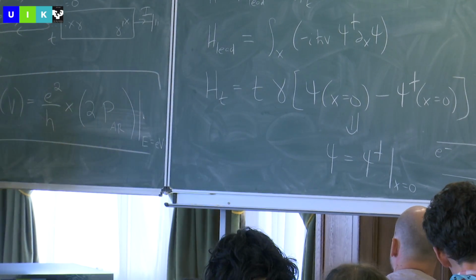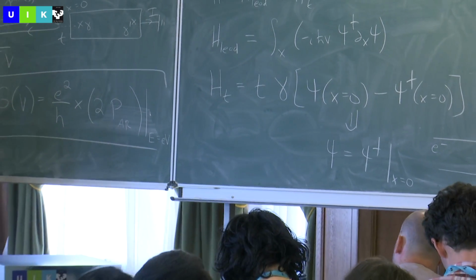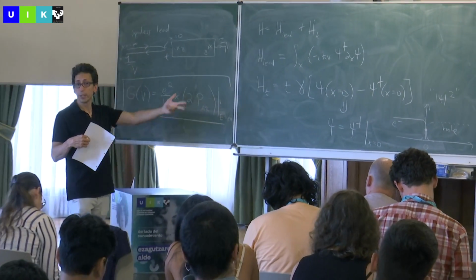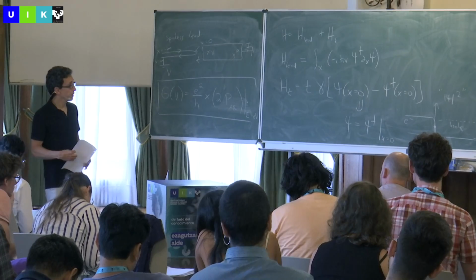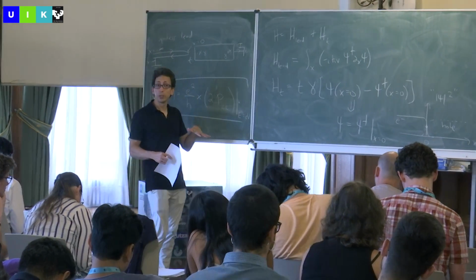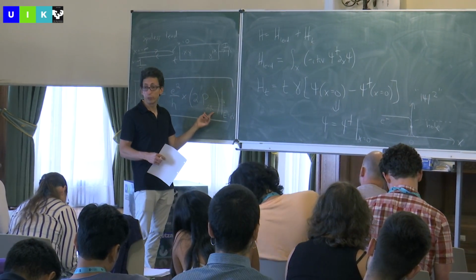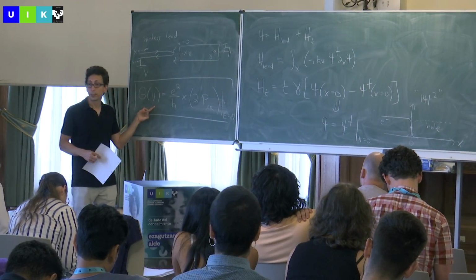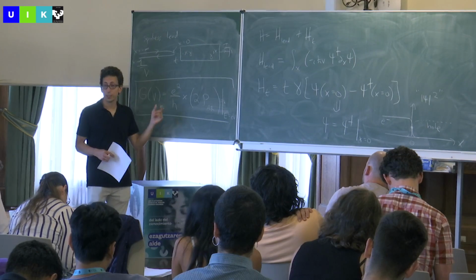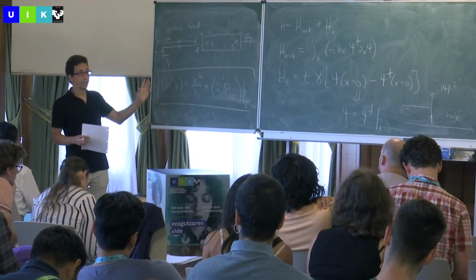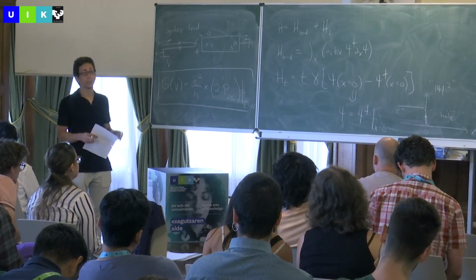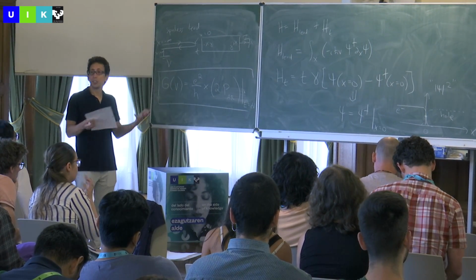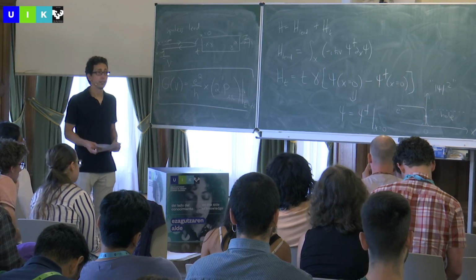This wave function describes a process where, with unit probability, I come in with an electron and I bounce back as a hole, depositing a Cooper pair into the superconductor. In other words, at low bias voltages, this Andreev reflection probability becomes 1, and you get a zero bias conductance which is quantized at 2e squared over h. Right, so this is the zero bias peak, which provides a very nice consistency check with the existence of Majorana zero modes.